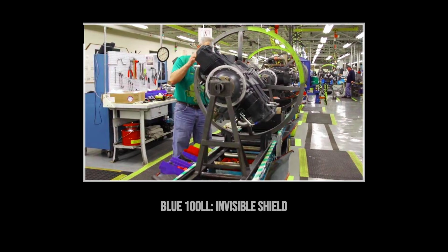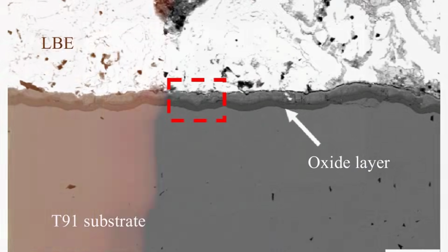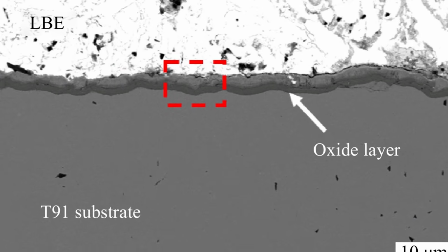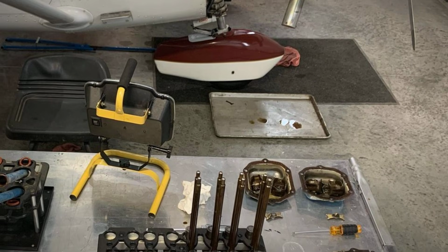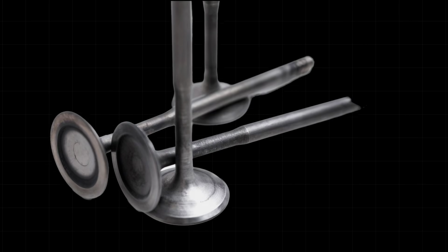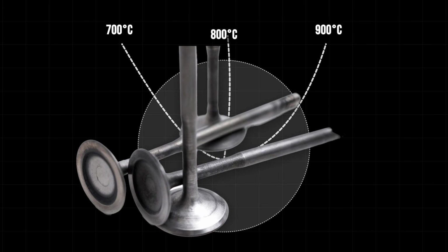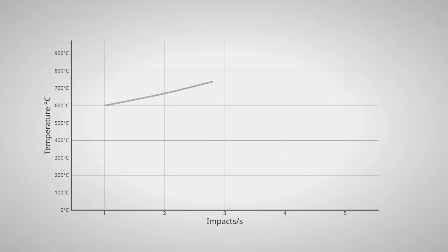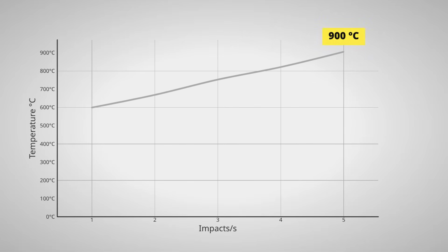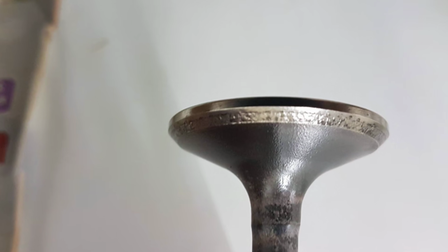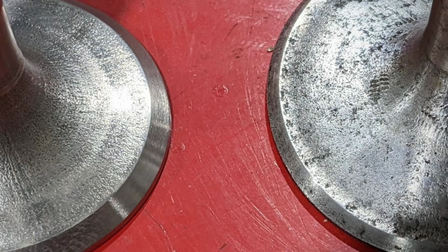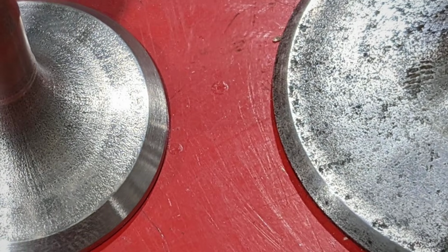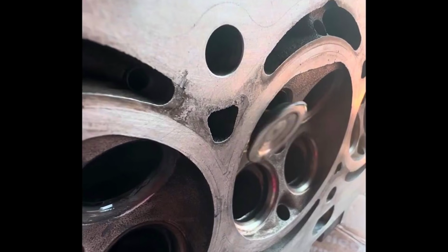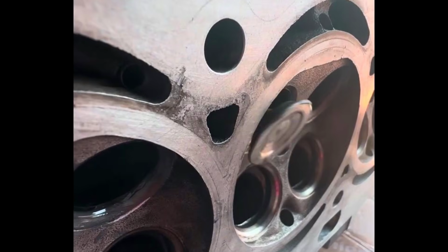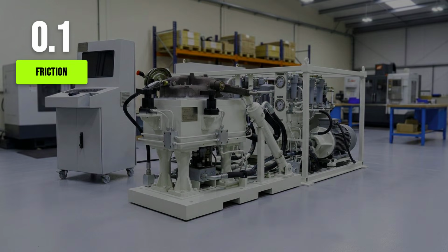Every time a piston fired, tetraethyllead burned into lead oxide, spreading a microscopic film across the hottest surfaces. That film did not just fight detonation. It formed a cushion, an invisible pad, between the exhaust valve and its seat, soaking up the hammer blows of combustion at 700, 800, even 900 degrees Celsius. Without it, the raw steel and iron would grind against each other, the valve face pitting and welding with every cycle. With it, the metal surfaces slid apart on a layer of lead, so slick, friction dropped from 0.3 to less than 0.1.